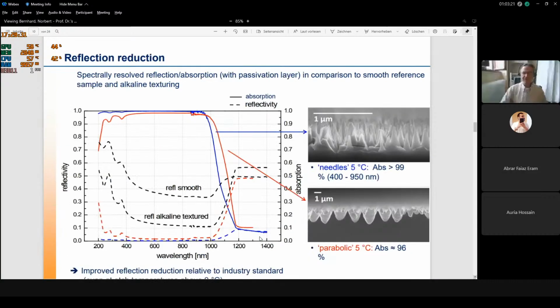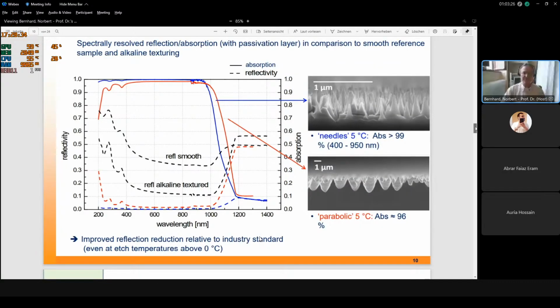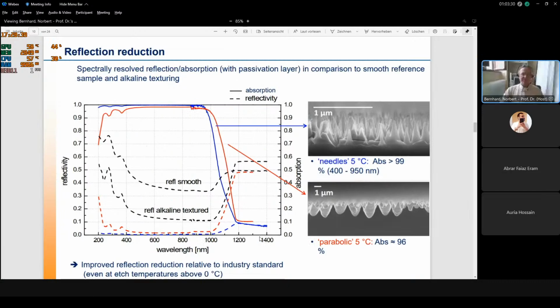Okay, here it's shown actually how much the reflection reduction is. And I will concentrate here on the dashed lines. The full lines, they are the absorption. I will concentrate on the dashed lines, which are the reflectivity. In this case, you see wavelength resolved. The upper dashed curve would be just the reflectivity of a smooth wafer surface. The second black curve here would be the reflectivity which can be reached by an alkaline texturing. And you see the red dashed curve, that is what we can reach by plasma etching with the moderate aspect ratio, and the blue dashed curve is what we can reach by plasma etching with the very high aspect ratios.